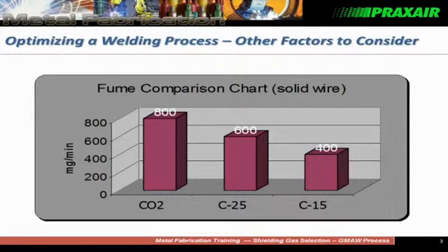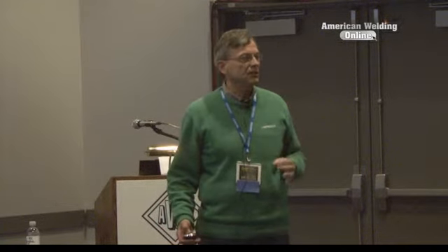We've heard about fume. You'll hear later, and you've heard a little bit already this morning, just changing the shielding gas for a gas-shielded welding process can lower the fume from CO2 to 25% CO2 in argon, 15% CO2 in argon. So as we lower the CO2 content of a shielding gas, it affects the amount of welding fume that's generated. So that's one thing we could look at.